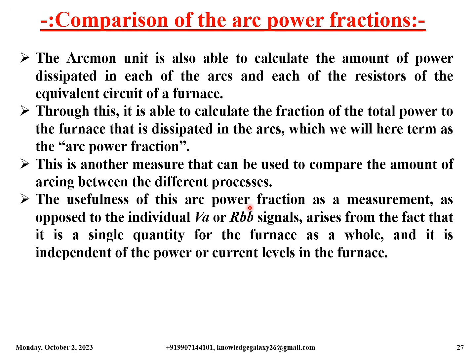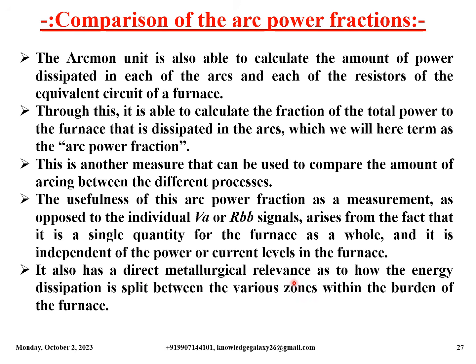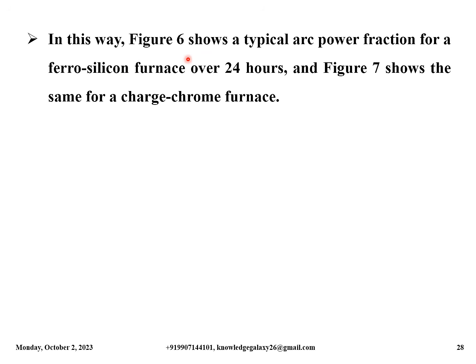The usefulness of this arc power fraction as a measurement, as opposed to the individual VA or RBB signals, arises from the fact that it is a single quantity for the furnace as a whole and it is independent of the power or current levels in the furnace. It also has a direct metallurgical relevance as to how the energy dissipation is split between the various zones within the burden of the furnace. In this way, figure 6 shows a typical arc power fraction for a ferrosilicon furnace over 24 hours and figure 7 shows the same for a charged chrome furnace in the coming slides.